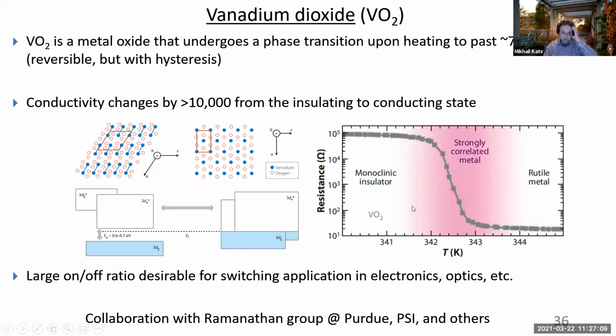So the famous one, the canonical one, is vanadium dioxide, which is a metal oxide that has an insulator to metal phase transition around 70 degrees Celsius, which results in dramatic changes in DC conductivity, in the crystal structure, and the band structure, and also in the optical properties. But we're starting to look at some other materials as well. I'll show you one in just a second.